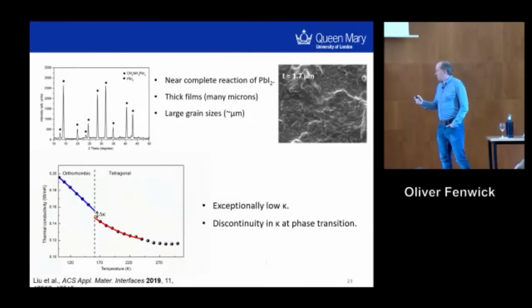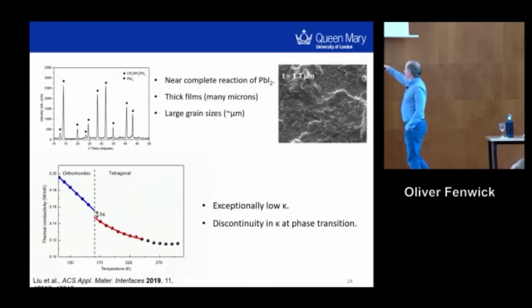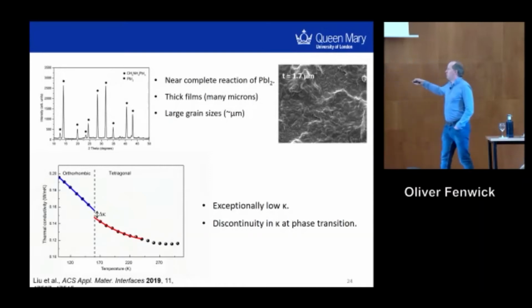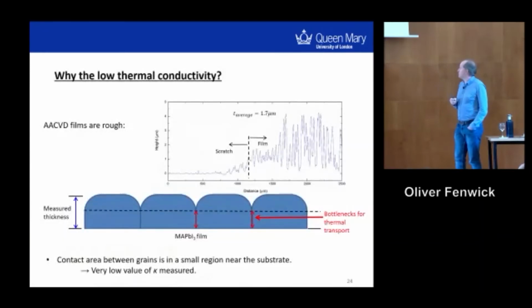Of course, we checked that we got methyl ammonium lead iodide on the substrate. It's not got such a preferred orientation this time, so you've got grains pointing in different directions and a small amount of lead iodide. And this is the thermal conductivity. We notice two particular things here. One, the thermal conductivity is exceptionally low. We're now below 0.2 watts per meter Kelvin, and at room temperature closer to 0.1 watt per meter Kelvin. And we also see a discontinuity in the thermal conductivity at the phase transition. We wanted to understand both of those things.